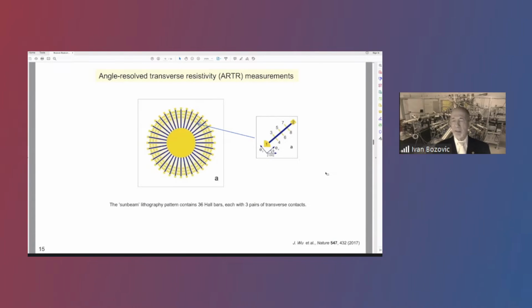And this must be true for every orthorhombic crystal. For this reason, we invented a new technique that we call angle-resolved transverse resistivity measurement. So we grow a film, lanthanum strontium cuprate film, by atomic-layer-by-layer molecular beam epitaxy. Then we pattern it into what we call the sunbeam pattern. It looks like this.